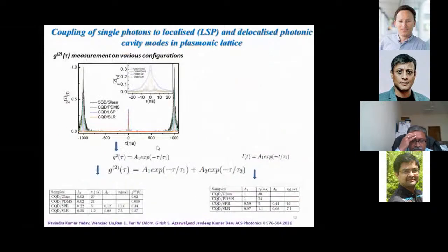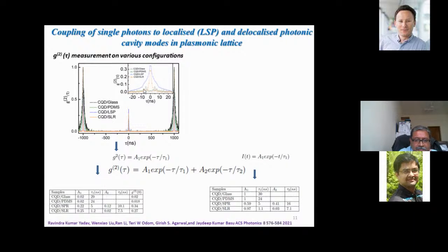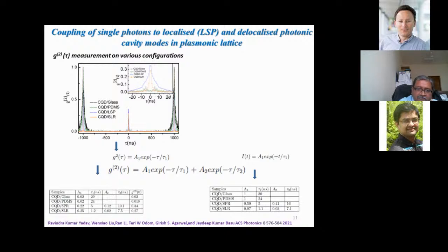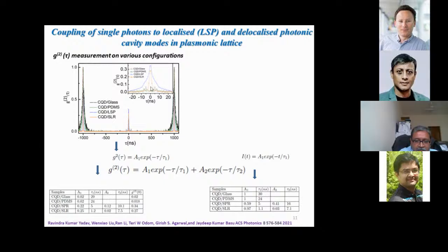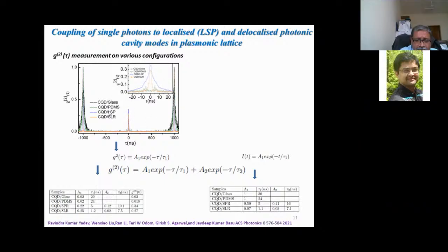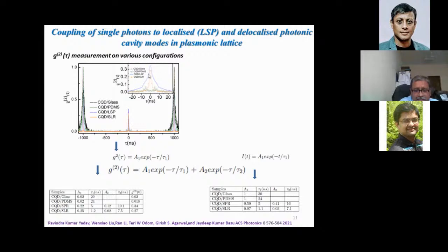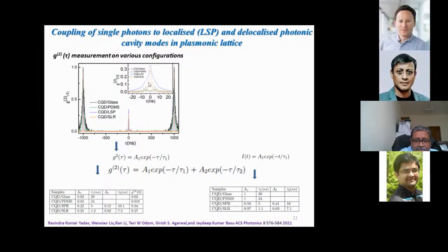So I mentioned single photon emitters. What is the proof? If you zoom in here, you can see that on glass it's almost gone. So it's really very high purity single photons coming out from this emitter. That is very encouraging. And then you see this dip. All of these are in the single photon regime. That means even when they are on the SLR, you still have them in the single photon regime, comfortably. But one notices that there is a slight increase here.